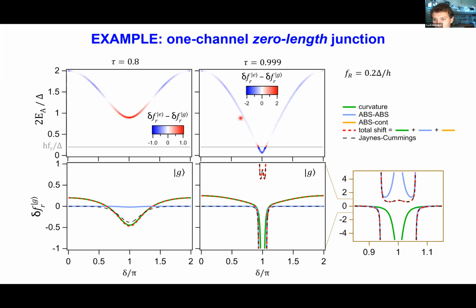Now in the second case, you see that this time the resonator shift in red, the curvature is not enough to capture the shift, and that this time the contribution from the virtual transitions between Andreev bound states is significant, and in this case you can really capture the shift only by a Jaynes-Cummings-like description. However, far from phase pi, Jaynes-Cummings would fail at describing the shift, which is still given by curvature.